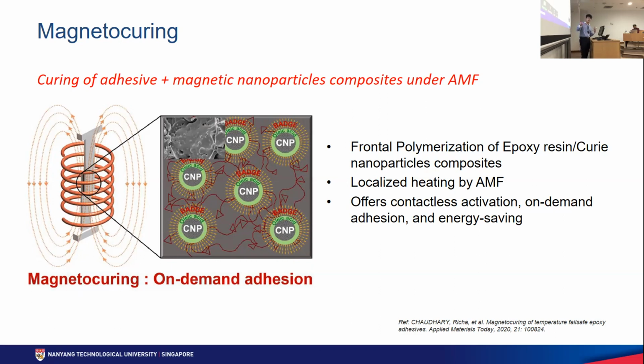You can see the illustration right here inside of a coil. In my work, I utilized a cationic polymerization scheme called frontal polymerization of these epoxy resin and magnetic nanoparticles. This method offers localized heating by the alternating magnetic field. So we're not heating the substrate, we're only heating the adhesive. It also offers contactless activation, on-demand adhesion, and it's also very energy saving compared to other methods.